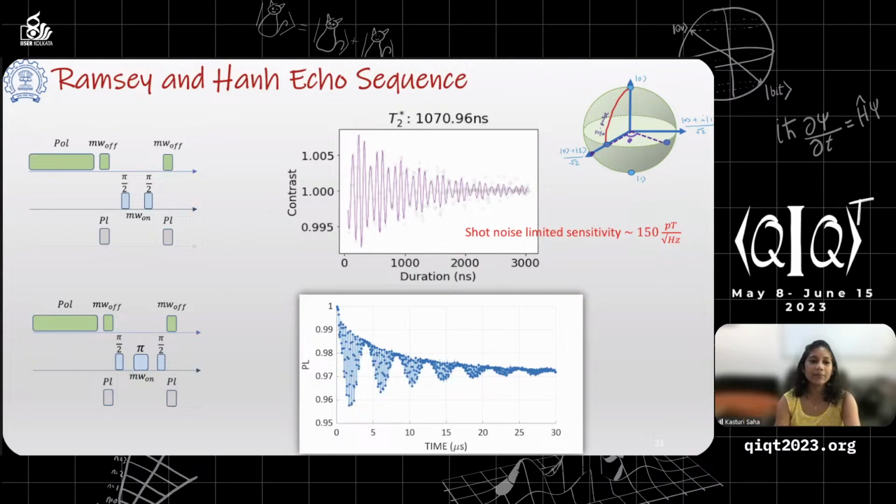Now, you can then perform Hahn echo, and NMR has defined a whole bunch of sequences that you can perform. We did some very simple ones like the Hahn echo here, and we've also done XY8, etc. You can see that very nicely. You can see that the echo is extending the coherence time, or the T2, of these NV centers. Of course, here you can see some more modulation, and that's because of the nuclear spin interaction with the electronic spin, and that comes up like a double electron-electron resonance or nuclear spin resonance.